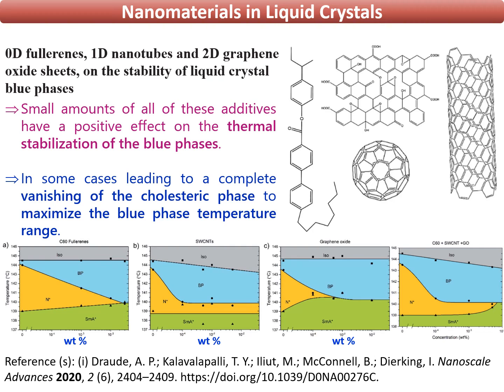In this example, zero-dimensional fullerene, one-dimensional nanotube, and two-dimensional graphene were mixed with a biphenyl-based calamitic mesogen, which is shown in the figure, at various weight percentages. As can be seen from the phase diagram shown below, the stability of the blue phase increases on increasing the weight percentage of nanomaterials. In some cases, it leads to the complete vanishing of the cholesteric phase to maximize the blue phase temperature range.